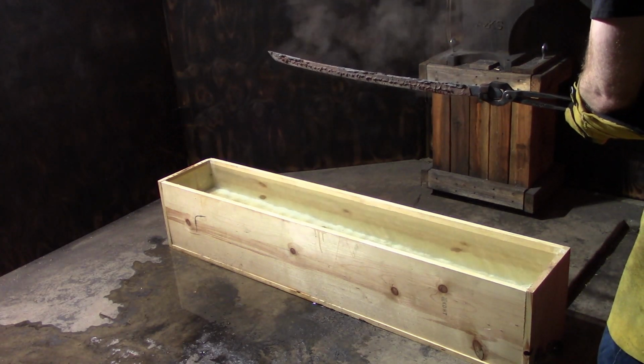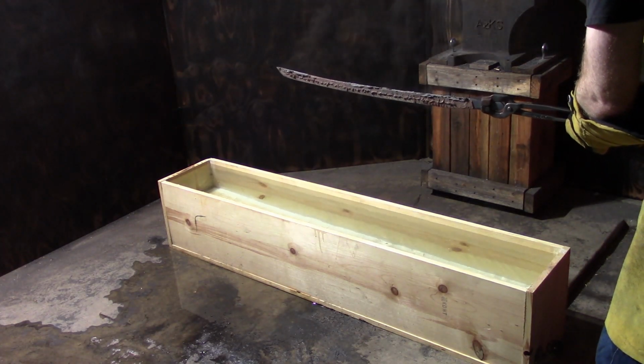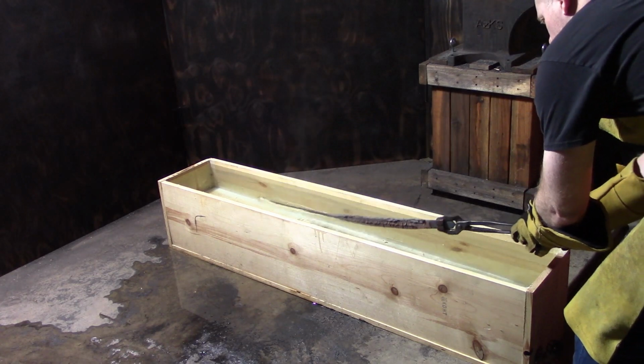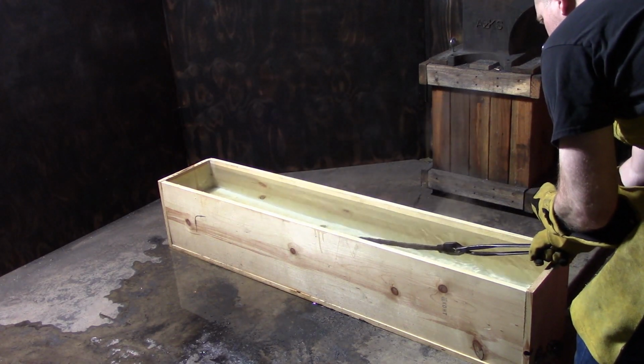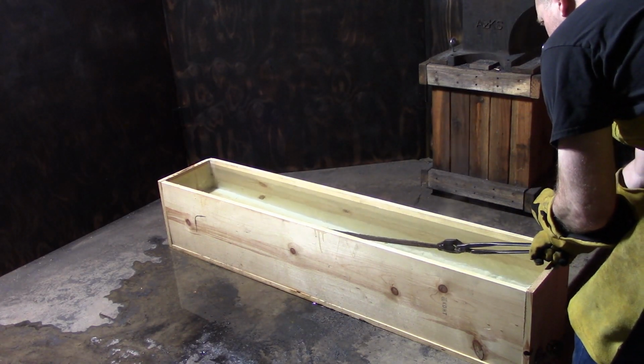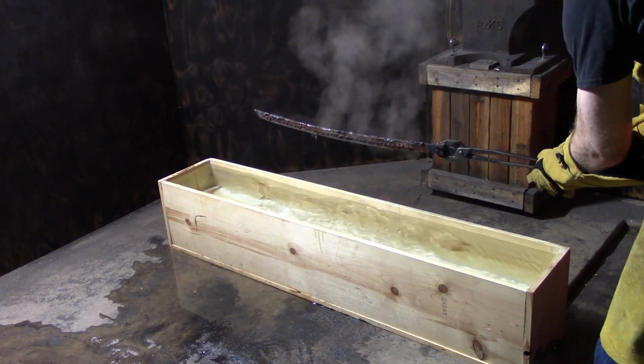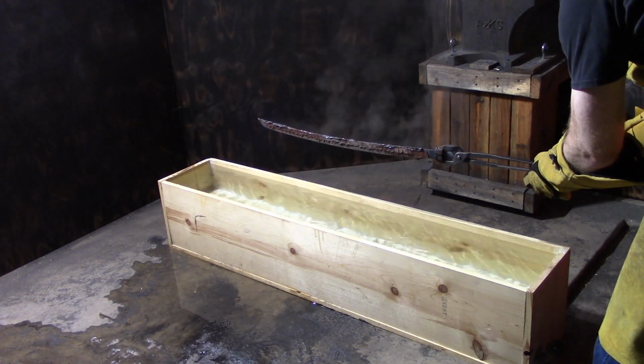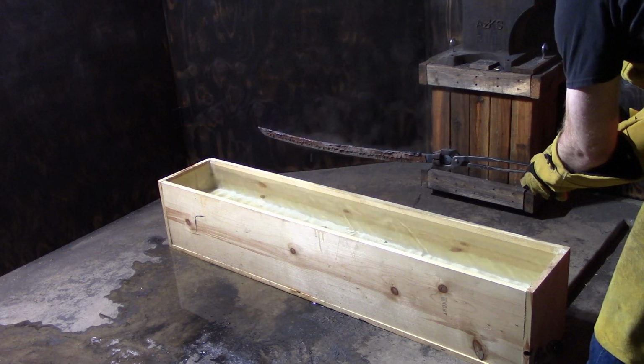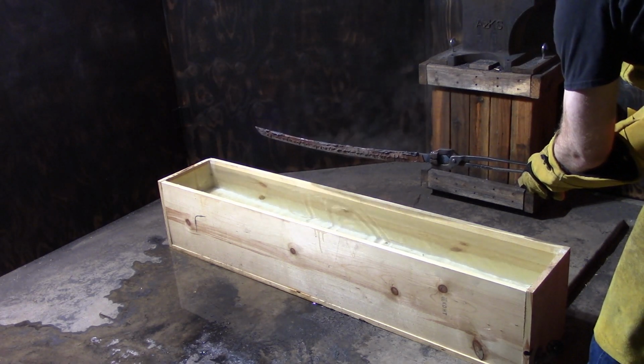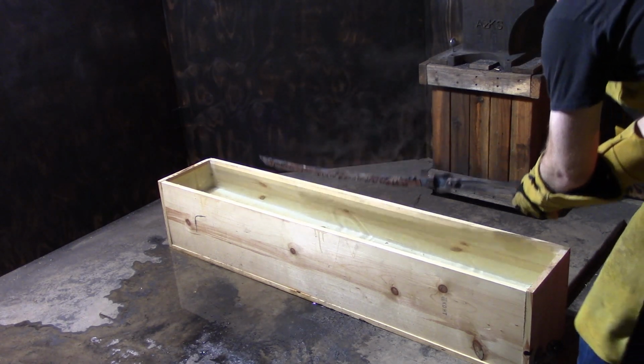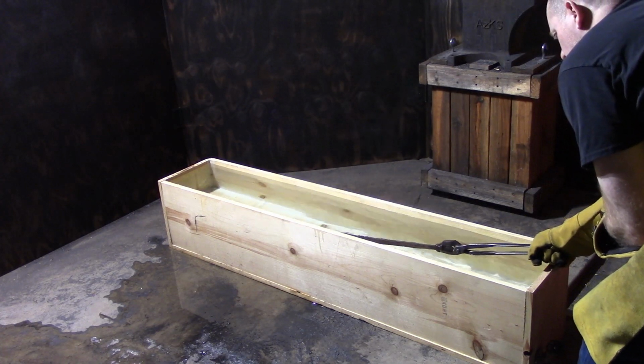I quench the sword for about 6 seconds, then I remove it from the water for a few seconds, then I put it back in the water and finish bringing it to room temperature. This quenching method is a bit harsh by comparison with some others that I've seen, and it does carry a bit higher risk of cracking the blade. On the other hand, it produces a bright, beautiful hamon, which is important to me, so I take the risk.